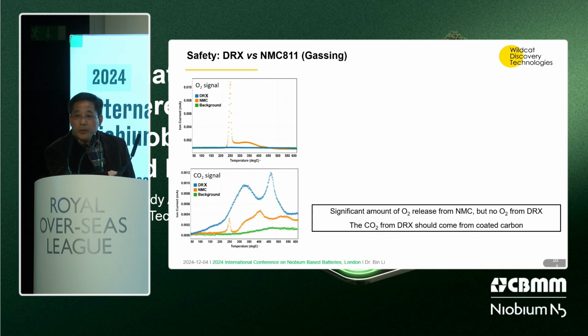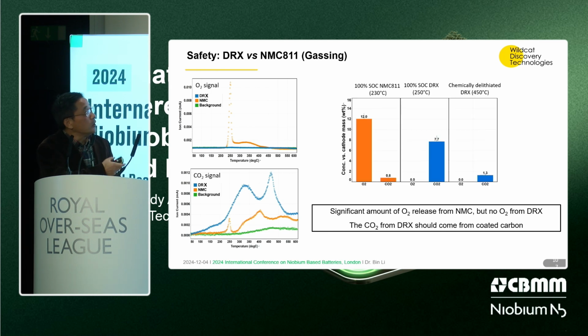And we do see some gas generation with our current DRX. What we see is a relatively large amount of CO2 generated. That is because our current DRX still has about 4% carbon content. How do we confirm this comes from the carbon, and not from generated oxygen reacting with the electrolyte to generate CO2? That's still possible. What we do is chemically isolate the DRX so you don't have the carbon. And here you see the oxygen is still zero and the CO2 amount is very little. This further confirms there's no oxygen release, and the CO2 comes from the carbon of the DRX coating.